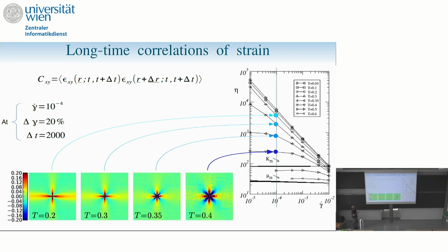The signature of the avalanches here can be read in the bias between the positive lobes and the negative lobes. When you have single events, the positive lobes and negative lobes have comparable amplitudes. That's the Eshelby signature. Look here. Here it's not as developed as there, but you see that already here you have a bias between positive and negative lobes, which are slightly smaller. And look, we are just barely in the transition from Newtonian to non-Newtonian. So what this tells you is that as soon as you get non-Newtonian behavior, you start to see correlations between events.